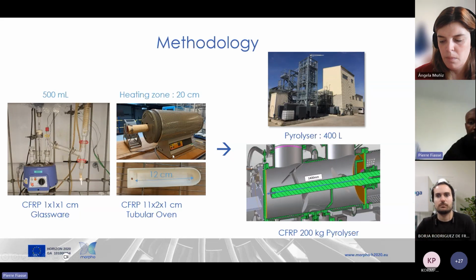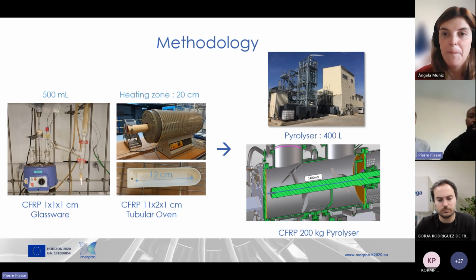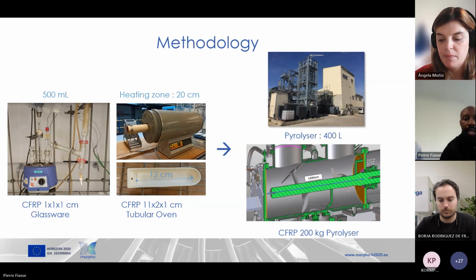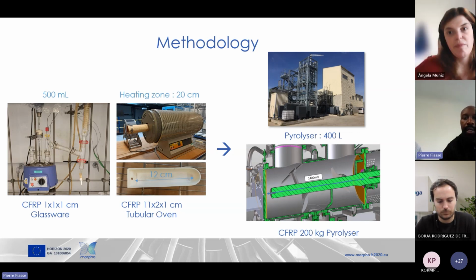For the tubular oven, it is quite the same characteristics, but we can increase the temperature compared to the glassware. Another advantage of the glassware is that you can directly see what happens during the pyrolysis process. Then, when all these tests were done, we went directly to the pilot. The pilot is a bigger reactor, so we can put more material inside. And for this one, the advantage is that we can get data like heat balance, because we can put more material inside.